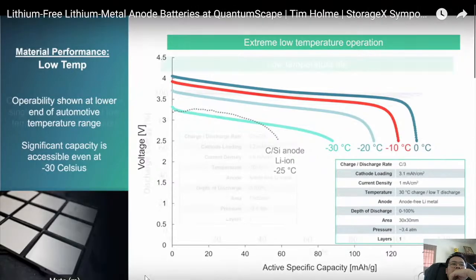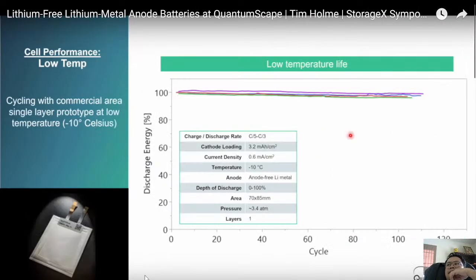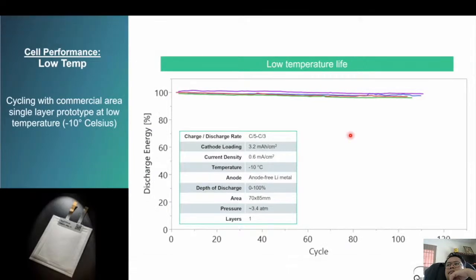So then we wanted to show cycling at low temperatures. This would be representative of real world winter driving conditions. Minus 10 degrees C, charging at C/5 and discharging at C/3 repeatedly. So this is showing performance of our cells across winter, showing that they retain a lot of capacity. And again, these were the same generation of cell, this single layer pouch cell, same cathode thickness, everything else. So I think solid state cells can work well at low temperature. This is some encouraging evidence.